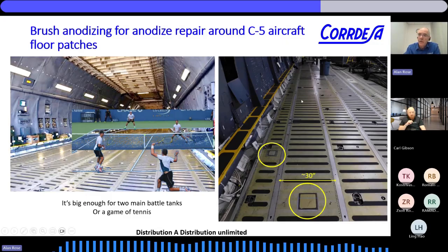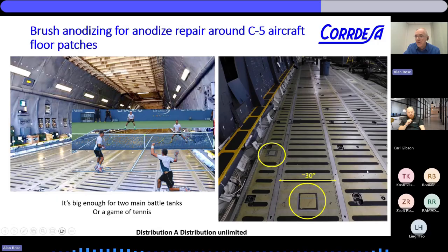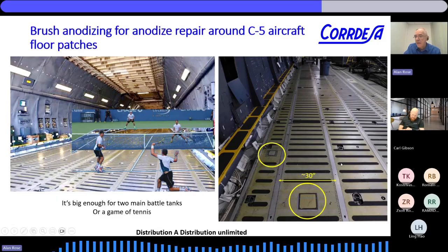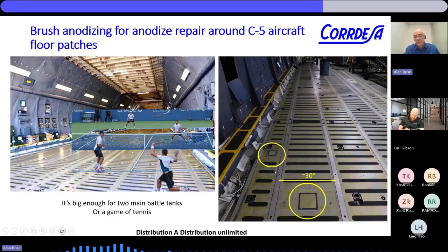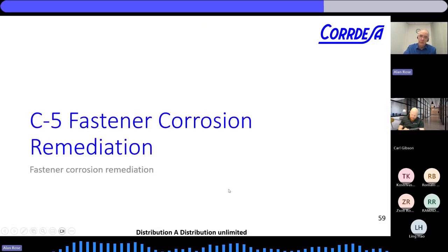And what they have with all this equipment, the floor gets damaged, and this in-tank anodize is really tough. And when they put a patch on, there's a standard repair for putting the patch on. They damage the anodize because they have to adhere the patch to the floor. So the anodize gets damaged, and they wanted a way of repairing that, and that's what we did. We created a repair for that.